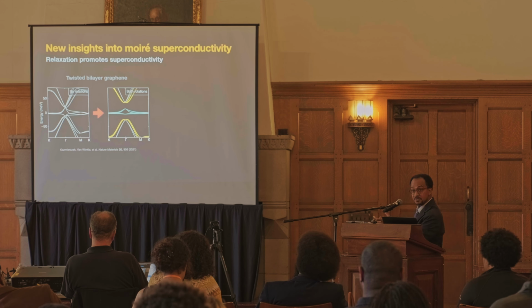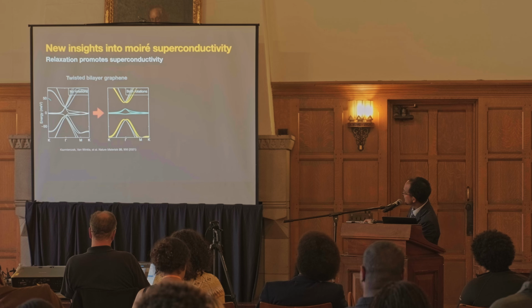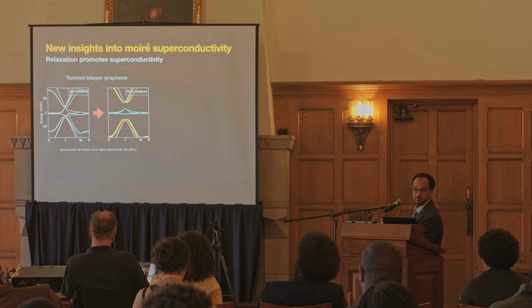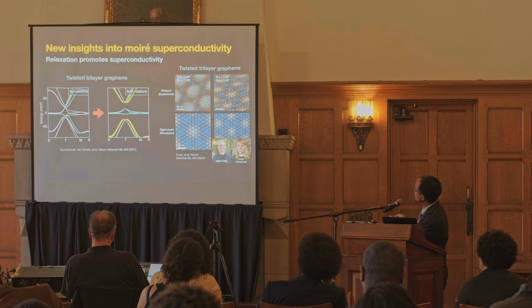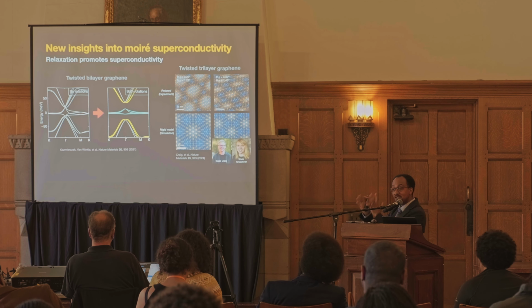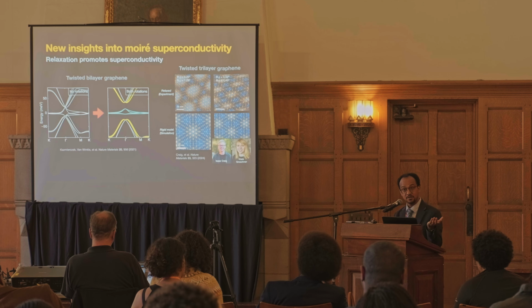In particular, it's a subtle difference, but it's an important one. This flat region over here is touching these more bendy regions. Without getting into details, what you see is that with what we discovered with our model, there is a gap above and below, right? And that makes a world of difference. And so that helped us to understand a little bit more about what allows these systems to display superconductivity. We have also looked at tri-layers. So now you have 3 layers that you can twist and mix and match in various ways. And it gets even more complicated and more interesting. And this electron microscopy tool that we developed allows us to be able to see these materials.